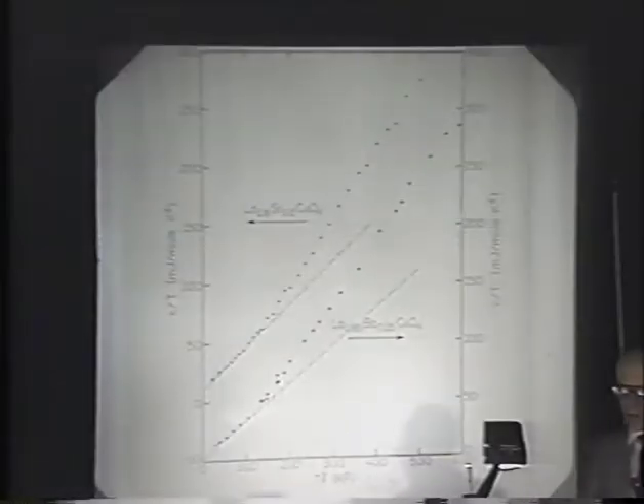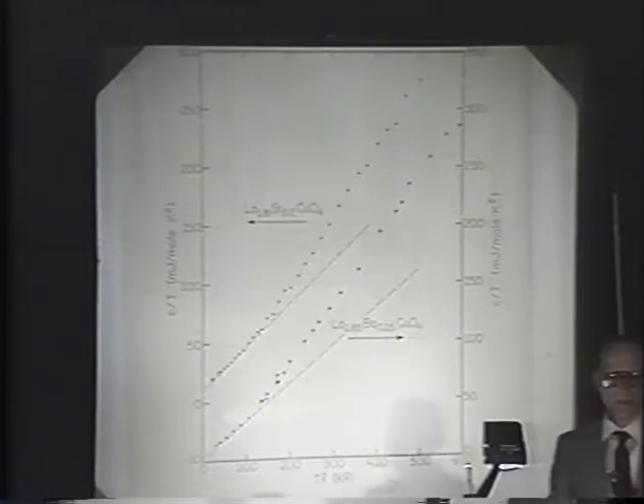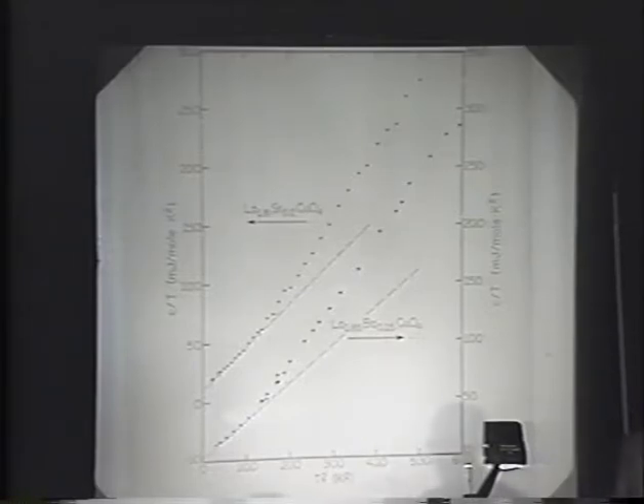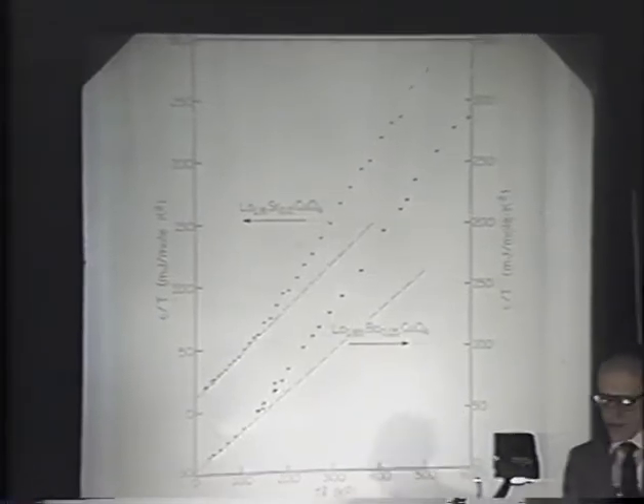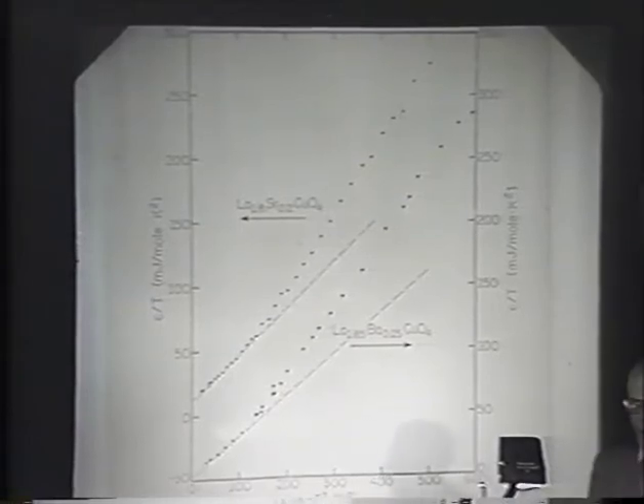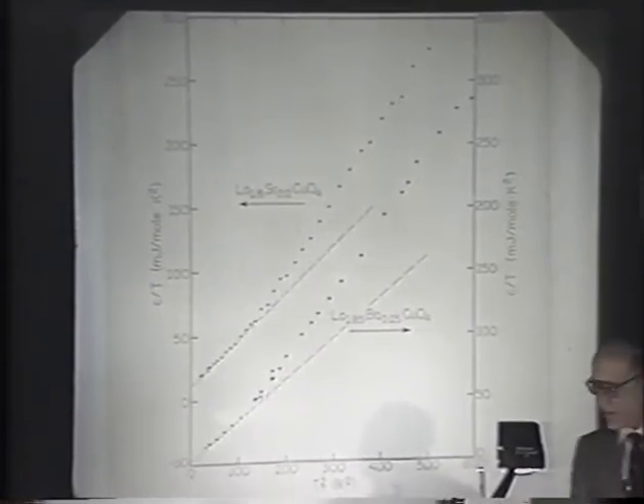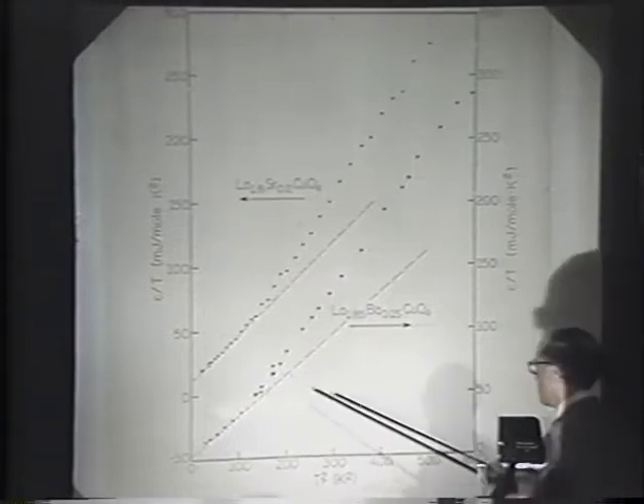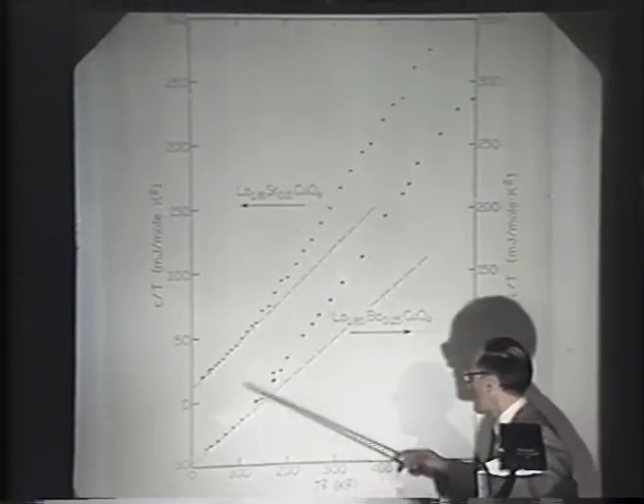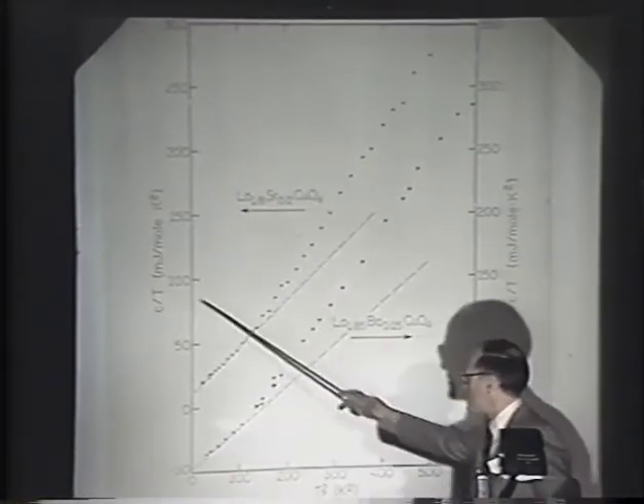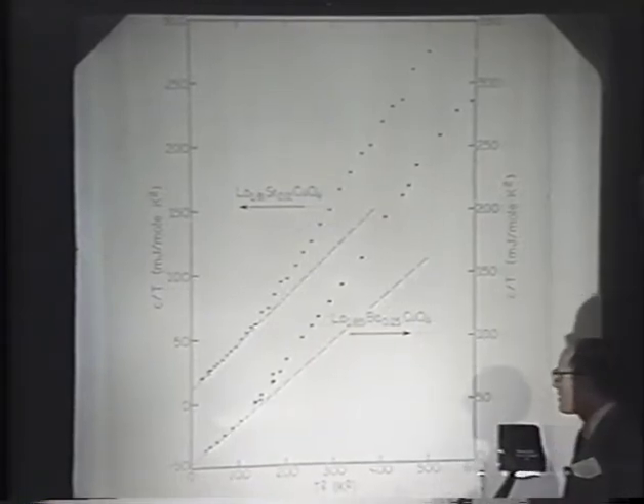Now, when you plot C over T versus T squared, it usually means you're working with a normal metal and you expect the specific heat to go as gamma T plus something proportional to T cubed. Nevertheless, we did this, and we've got something kind of interesting, namely that for both compounds, the specific heat is a linear function here at low temperature. I mean, C over T is a linear function of T squared.